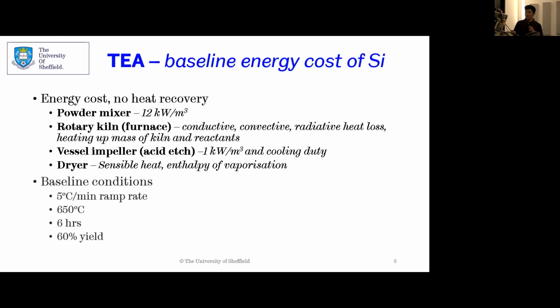So the baseline conditions I'm using to build this economic model is a 5 degrees C per minute ramp rate up to 650 degrees Celsius. And then the hold time is not really reported consistently in the literature, so I measured this in the lab and I put this into the model.